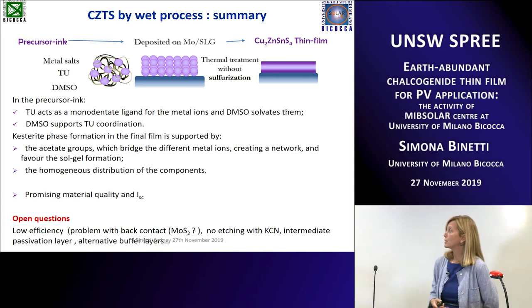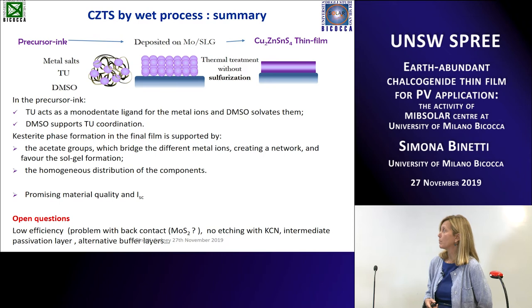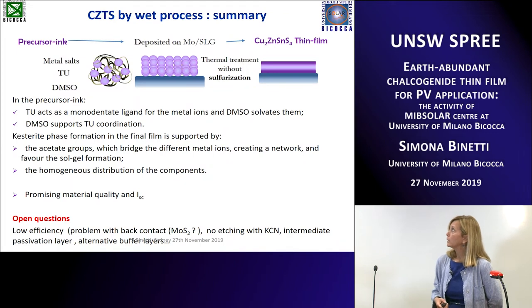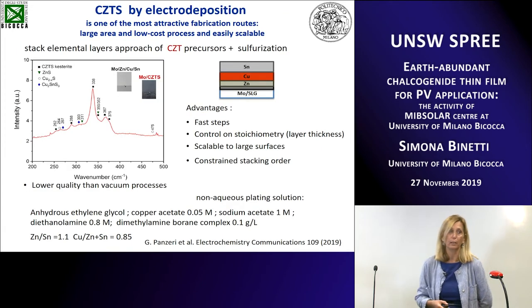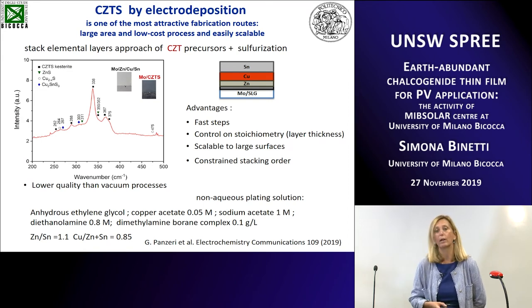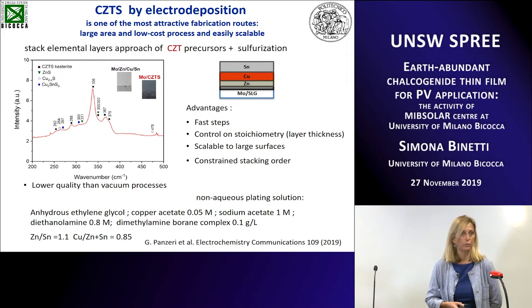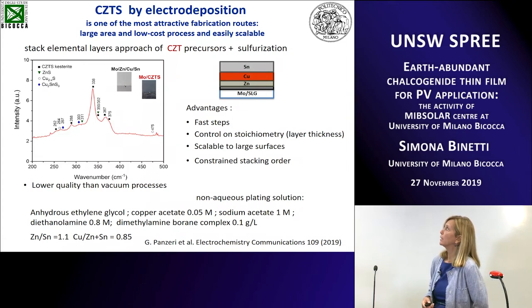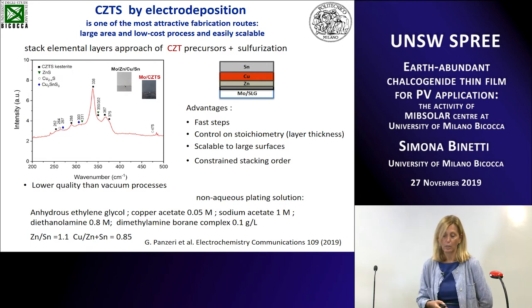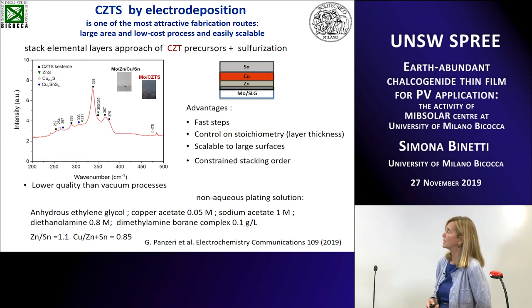And we are also studying the buffer layer, mainly deposited by an atomic layer deposition, ALD, system. On Kesterite, we are also working in collaboration with another group at Politecnico di Milano, another university, quite important, an engineering one. They are in charge of the electrodeposition system, so they are electrochemistry researchers. And so they are studying how to use electrodeposition for making Kesterite solar cells, because electrodeposition is one of the most attractive fabrication routes: it can be used on a larger area, and it's also a really low-cost and easily scalable process.